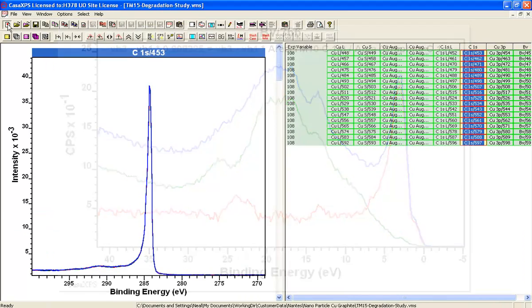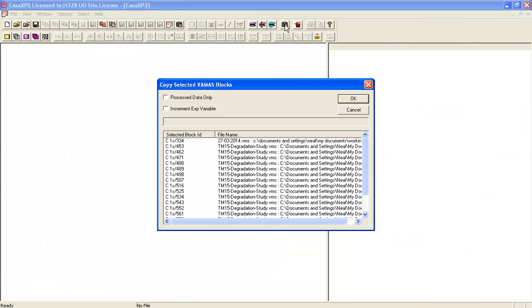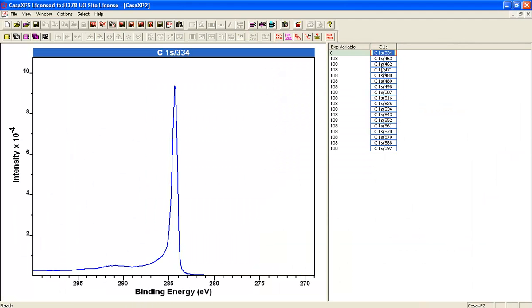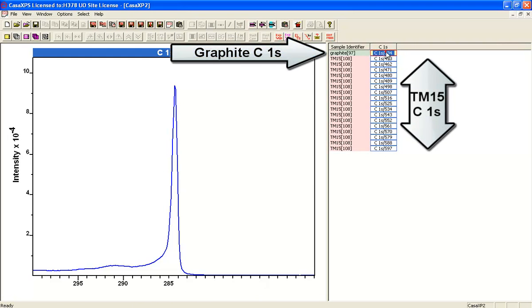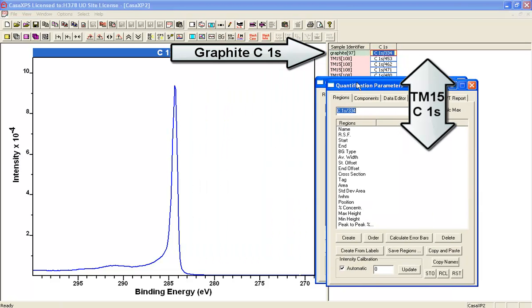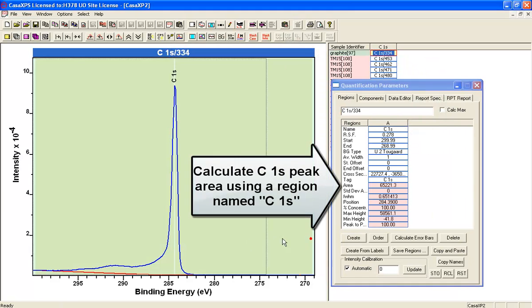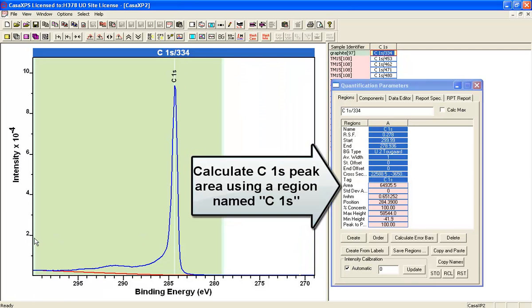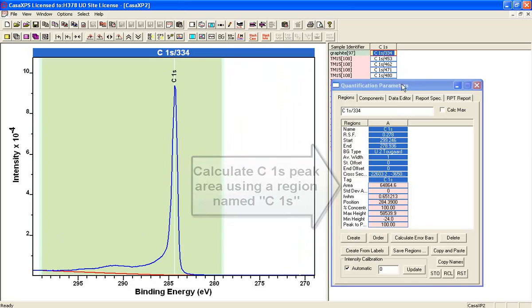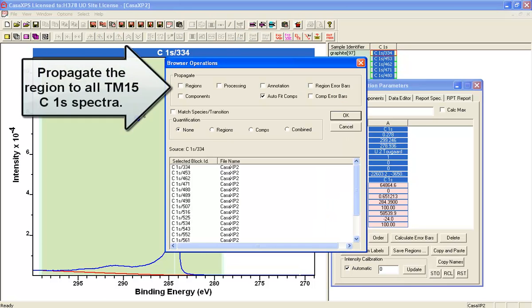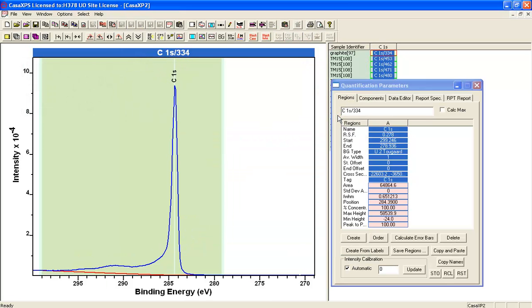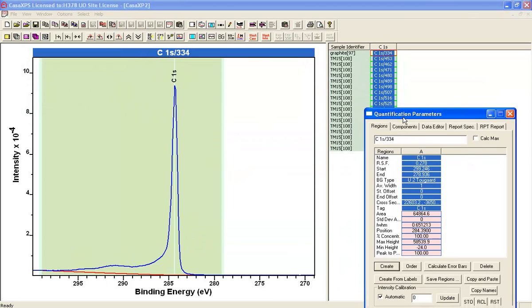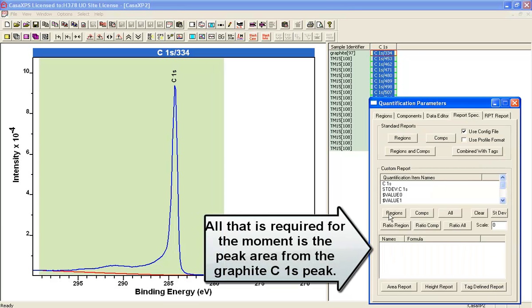The way we're going to do this is to calculate a proportion that is required for each one of these measurements to remove from the copper nanoparticle valence band spectra the graphitic form. We'll begin by defining some regions on the set of carbon 1s spectra from the copper nanoparticles and also from a graphite sample that is a standard material for which we have both the C1s and the valence band.